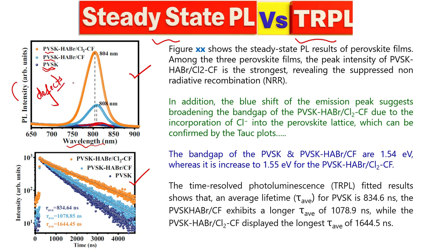So this means the excited electrons are basically lost, and those electrons are lost because of non-radiative recombination. This is very, very important. Non-radiative recombination means that, for example, when an electron jumps from the valence band to the conduction band, in the conduction band or in the higher states, there are many defects there. So the electron is basically lost in those defects. The electron recombines there, but there is no emission of photons. The electron is lost because of heat or phonons, etc. This is why it is called non-radiative. There is no radiation in this recombination, and that is detrimental for the device.